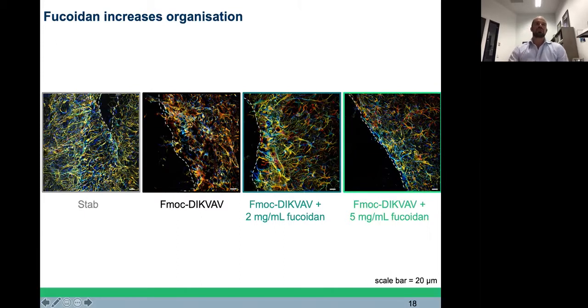Now, importantly, we were confused for a long time why the stab looked worse than the unfunctionalized materials. And basically what's happening here is you can see the void's actually quite small comparatively to these ones. What you get is a whole bunch of tissue collapse into that void. So you're basically getting micro tearing through the whole brain parenchyma, and that's resulting in increased activation. So the deeper we go into the tissue, there's still a lot with a stab of reactive astrocytes. But just by having that physical support here of the hydrogel, we've reduced a lot of that. And then when we present that fucoidan, we switch their behavior from this is still reactive, very disorganized, very fibrous, to these sort of highly organized cells that look nearly like starfish.